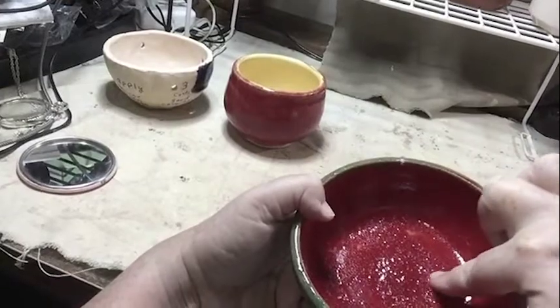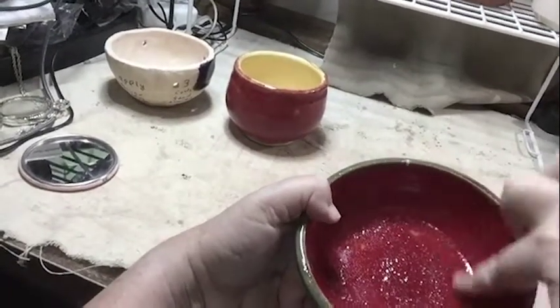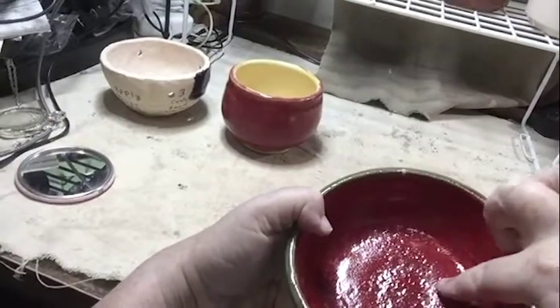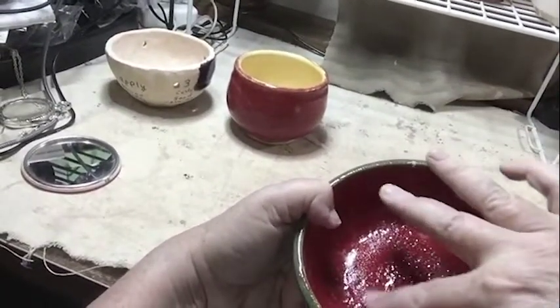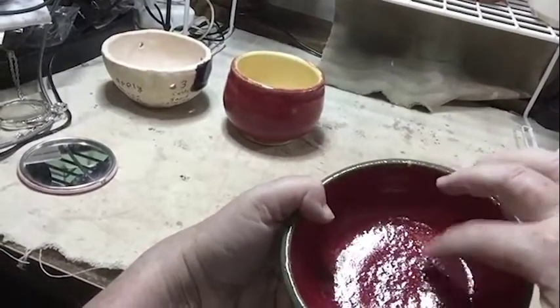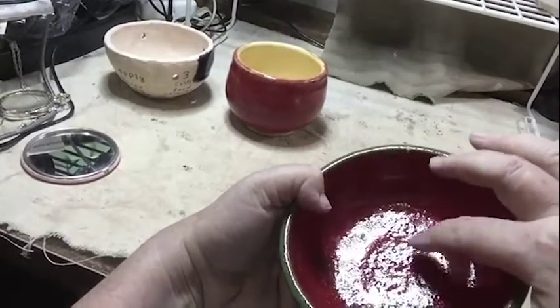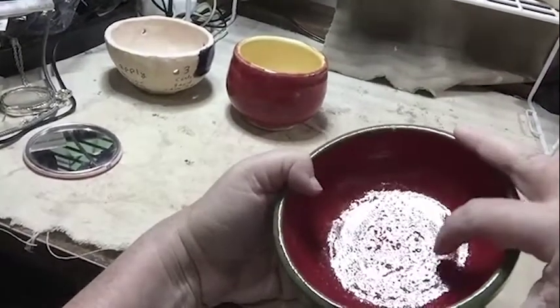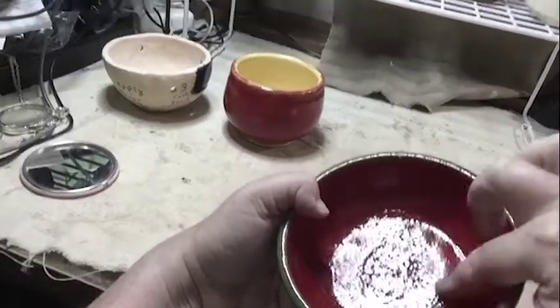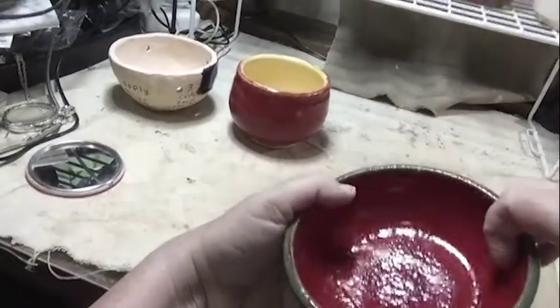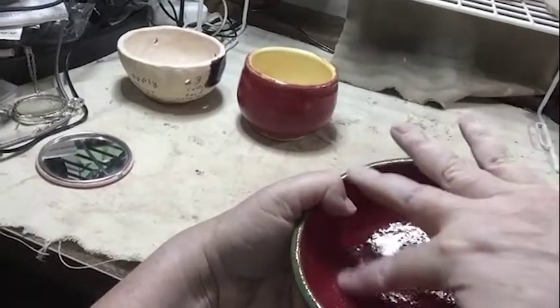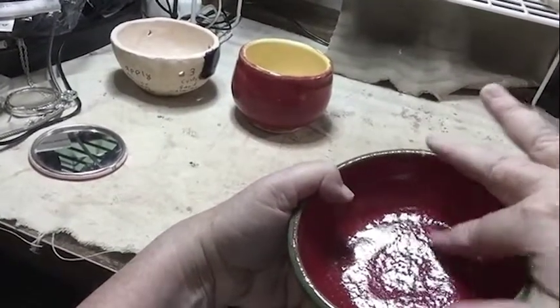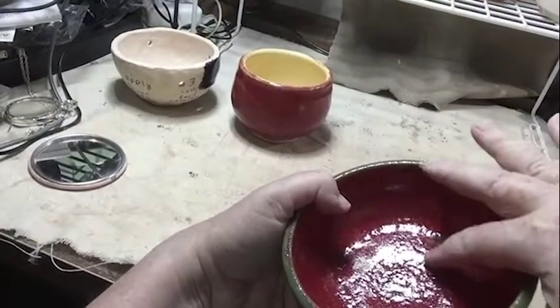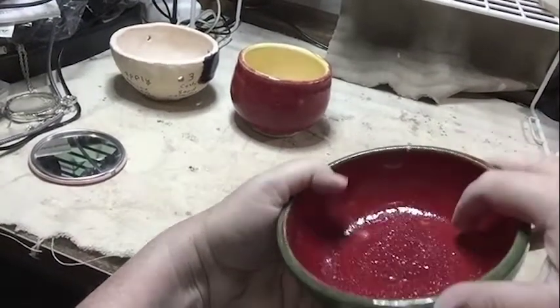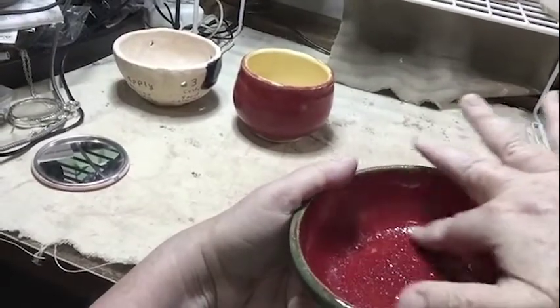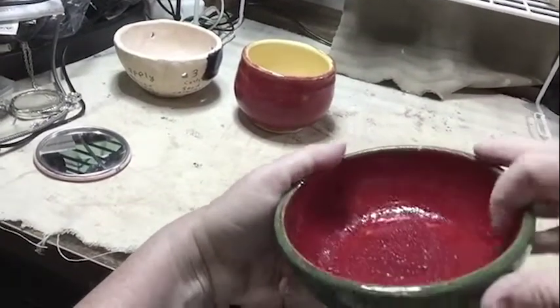So the same thing, the glaze ran down the sides. It was caught, of course, in the bottom of the piece here, but then it created this kind of pancake of glaze here that got so thick that it was difficult for the chemicals that are in the clay that get released when you're firing the piece to actually penetrate through the layer of glaze that was on there. So I've got this kind of volcanic looking surface at the bottom there, where you can see the glaze was very thick, and those bubbles just got through the surface of the glaze, but it was just not enough to smooth out the surface and finish that off there.